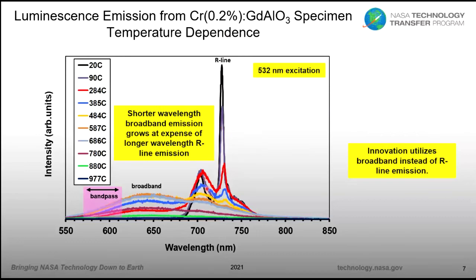As you increase the temperature, though, you populate that higher level and you get emission from it, from the relaxation. That's the broadband here. As you increase the temperature, that becomes more prominent at the expense of a reduced R-line emission. Until when you start getting around 1,000 degrees C, all you see is the broadband, and there's no R-line left. So that's the basis of our approach, besides the selection of the material, is to use this broadband emission.